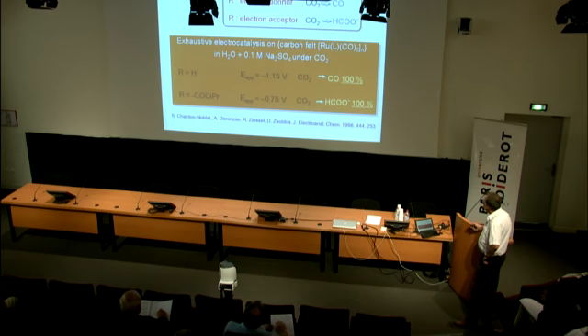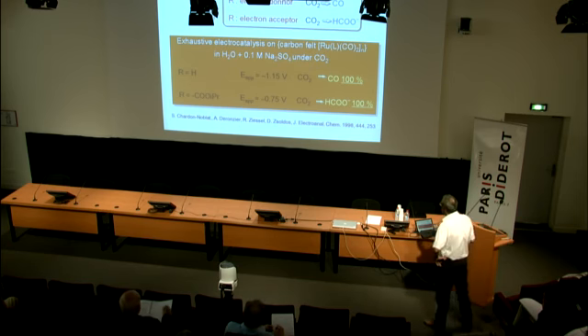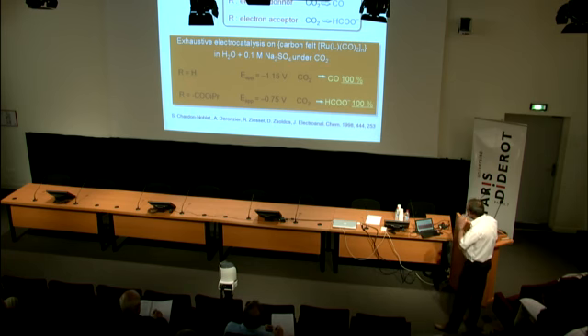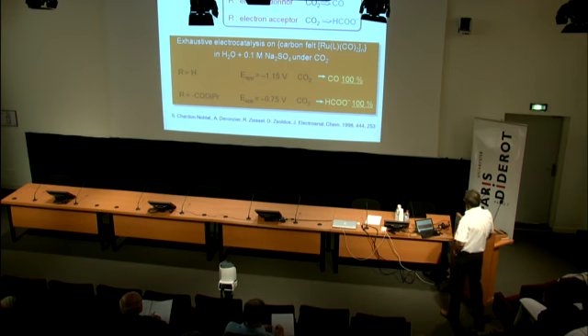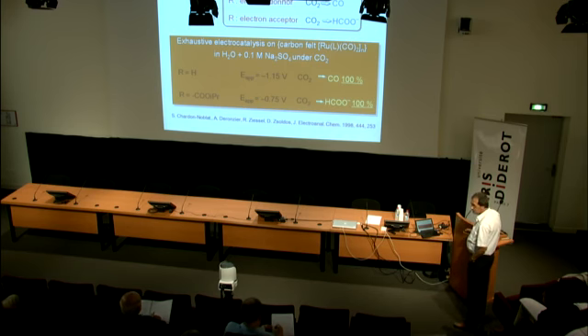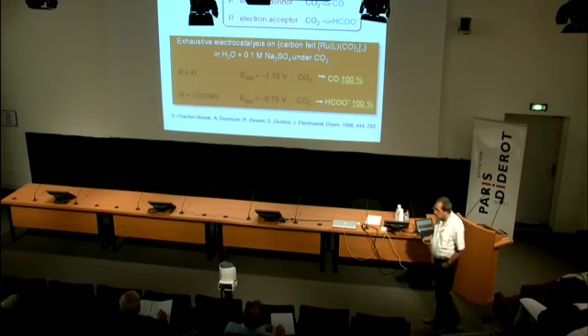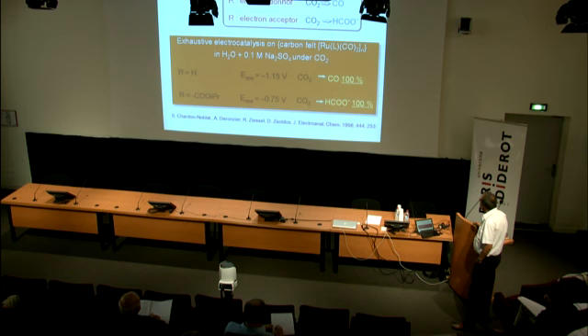For instance, exhaustive electrolysis on the carbon felt of the film in pure water with sulfate as electrolyte. If you use the polymer with a classical bipyridine, you apply that potential, you go with quantitative yields to CO. And if you use an ester group in this place here, at that potential, and you can see that this potential is less than the thermodynamical potential of the reduction of CO2 into formate. It's a real catalysis, and the selectivity is crazy quantitative in this condition.